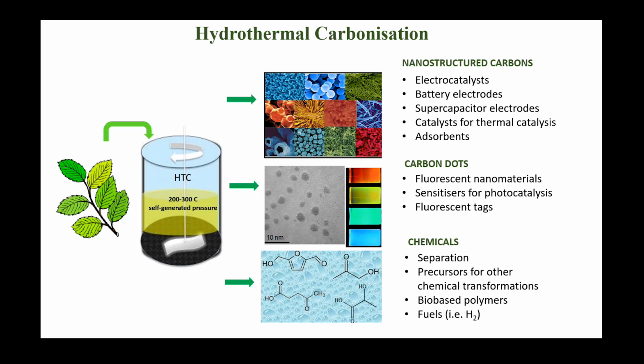into carbon materials. So what's happening here with biomass is that through a process that's similar to natural coal formation, but rather than waiting hundreds of millions of years, you just wait about a few hours, you can turn biomass into carbon. And it does this with some heat, but not too much heat, about 200 degrees, and under self-generated pressure between 30 and 50 bars, depending on the loading and the conditions that you work in.